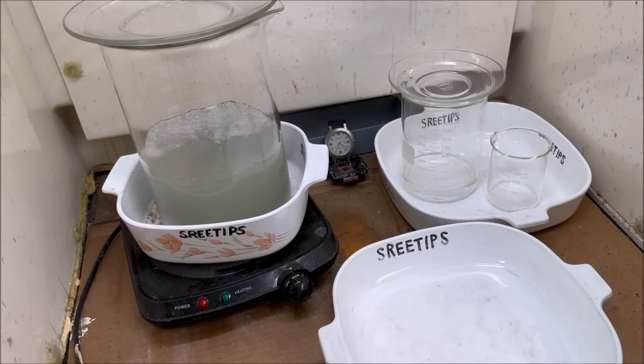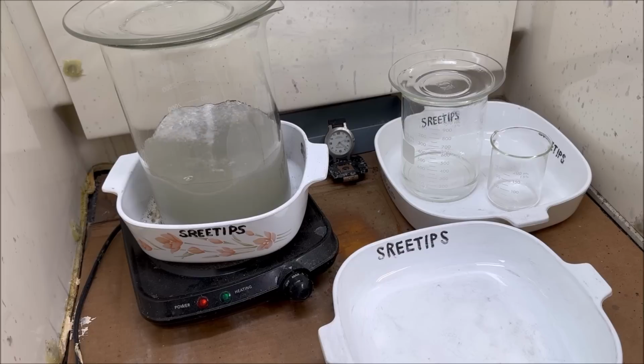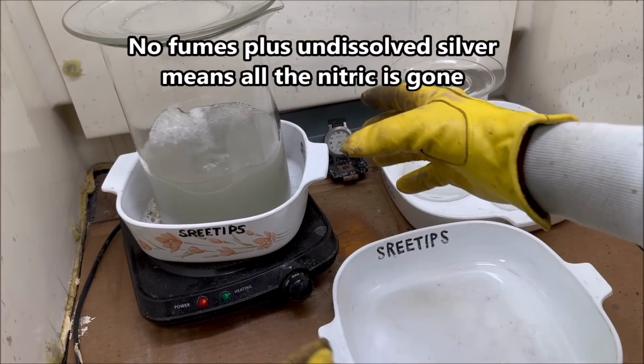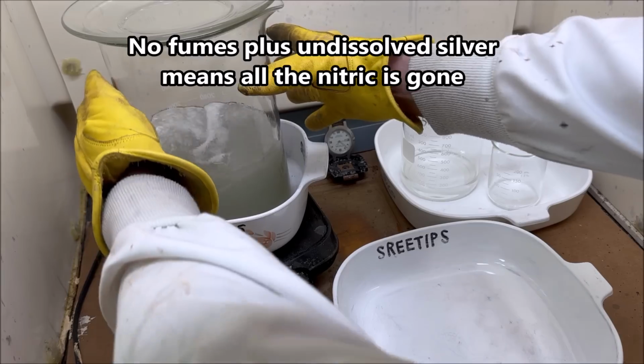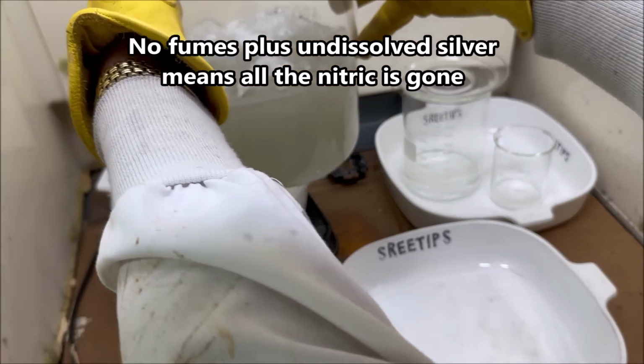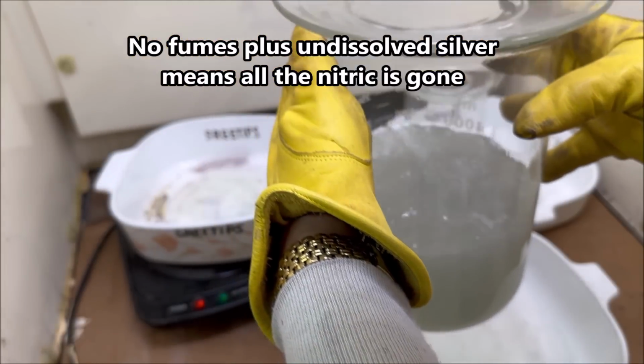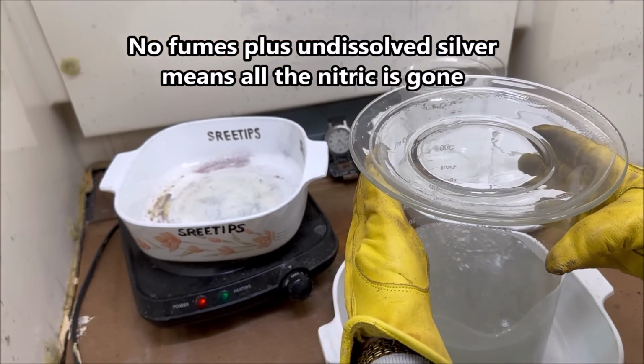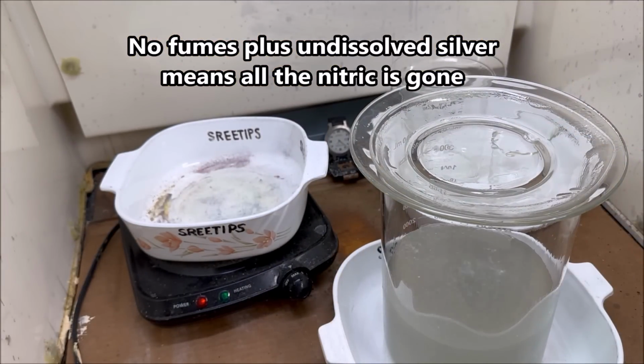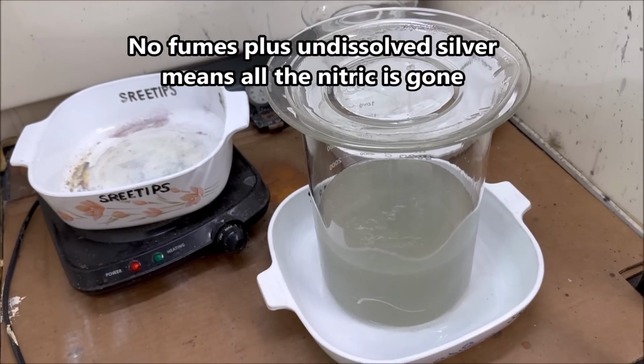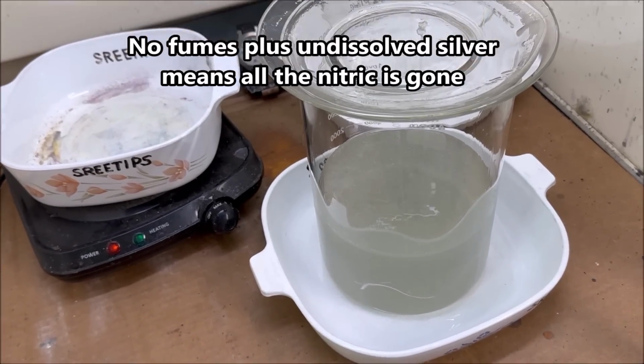We've got the electrolyte on a rolling boil. There's no fumes in there, and that tells me that every bit of the nitric acid has been consumed now. So we're going to pull this down off the heat. And if you notice, there's still a little bit of silver left down in the bottom of the beaker.